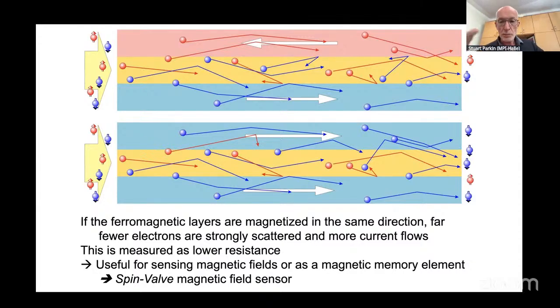And this we call the spin valve. In other words, by controlling the orientation of these two magnetic layers in this sandwich, if the copper layer is sufficiently thin compared to the mean free path or the scattering length of the electrons, then you can change the resistance. Now, it turns out we proposed we could use this as a magnetic field sensor, a spin valve magnetic field sensor to detect external magnetic fields.